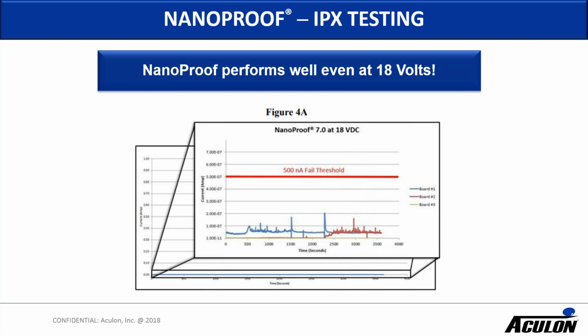As you can see here, this is an example of a 7.0 test run under 18 volts. This was in water for a significant amount of time. The failure threshold is very, very low. It's at 500 nanoamps, and you can see that on one of the tests there are some spikes up to 200 nanoamps. The other two tests didn't even break. One got up to about 150 nanoamps, and the other didn't even break 100 nanoamps.